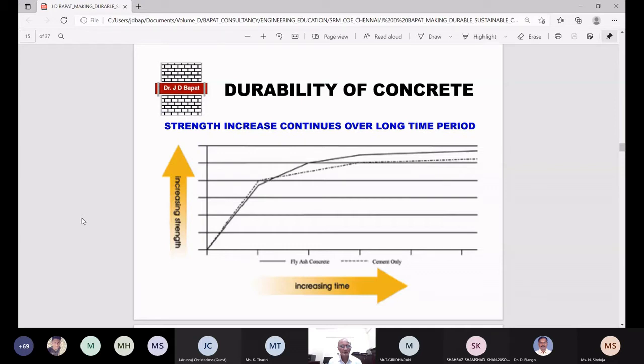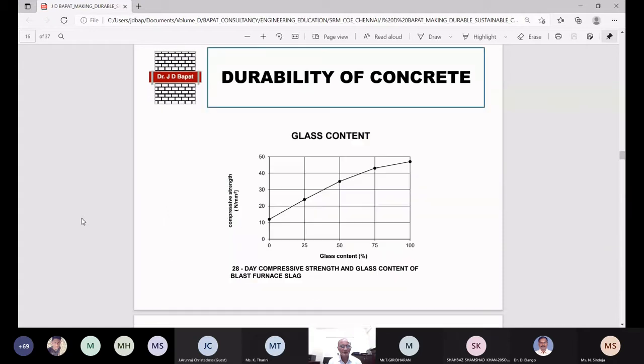The same is the case with blast furnace slag, but blast furnace slag strength is very much proportional to the glass content. I have already shown you in our standard we not only specify the quality index, but we also specify the glass content, because glass content has a relationship with the strength of concrete. So it is very important. That is the reason why the Indian standard specifies both the quality grade as well as the glass content. You can see in this plot, as the glass content increases, the compressive strength of concrete increases.